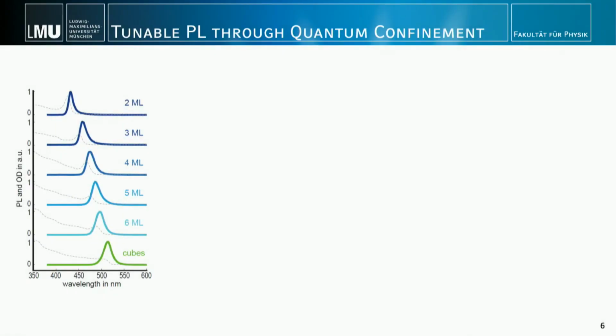Now let's take a look at the actual optical properties in detail. Here we see the PL spectra of several samples of different thicknesses, and you see this tunability throughout the blue range into the green, basically from dark and sky blue towards green. Every peak is quite narrow, and we don't have overlaps between the samples, meaning that each sample really contains only nanoplatelets of the same thickness.